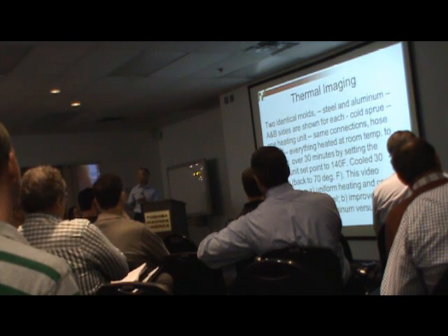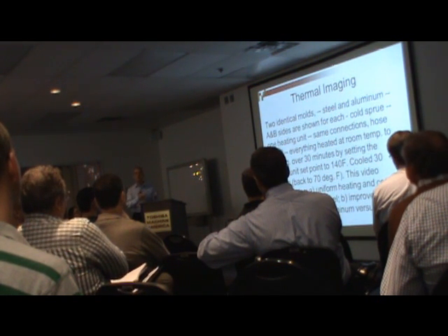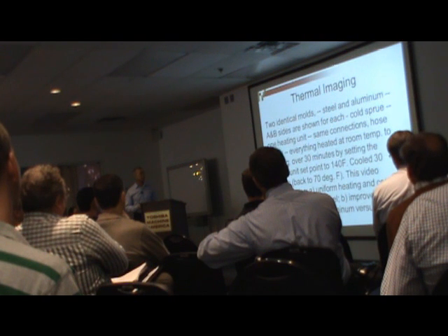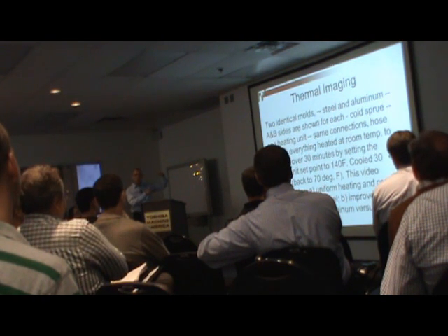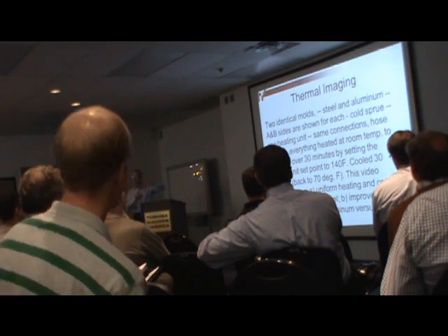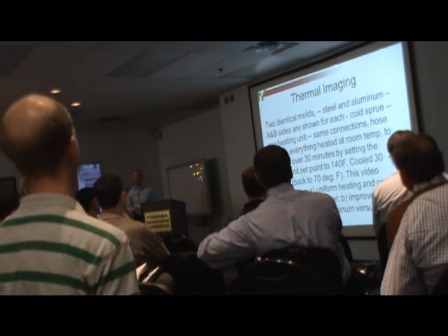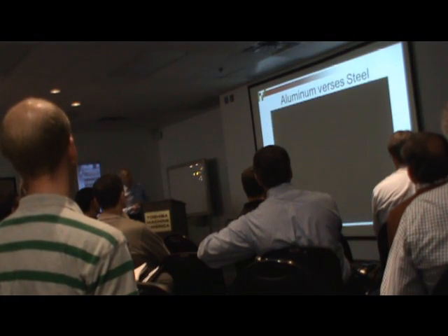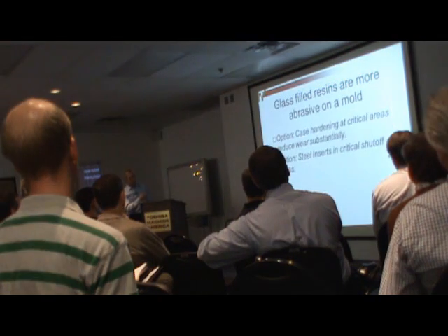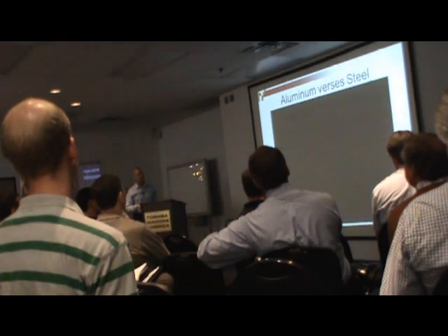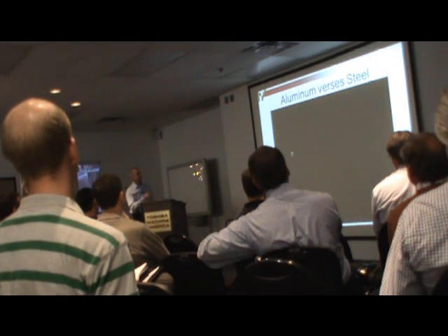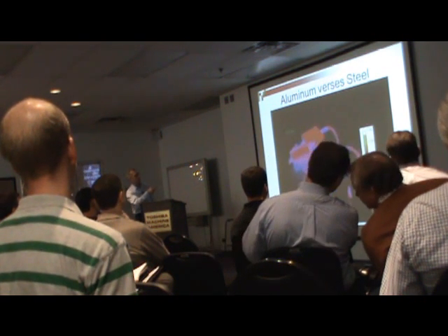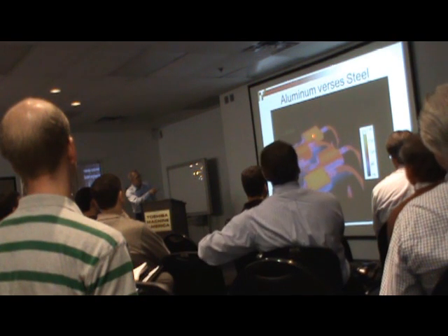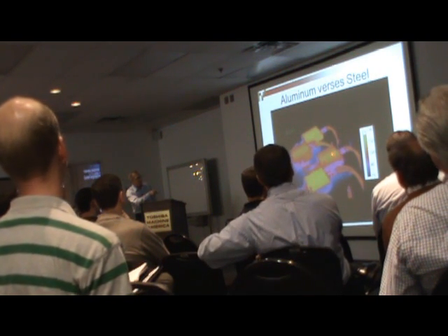Over 30 minutes it's taken to get up to 140 degrees using the same thermolator. And after they reach that 140 degrees, they drop down. It takes about 30 minutes to drop down to, I believe, 70 degrees. So what you're going to see is this one and this one right here. These are aluminum, and this is steel.